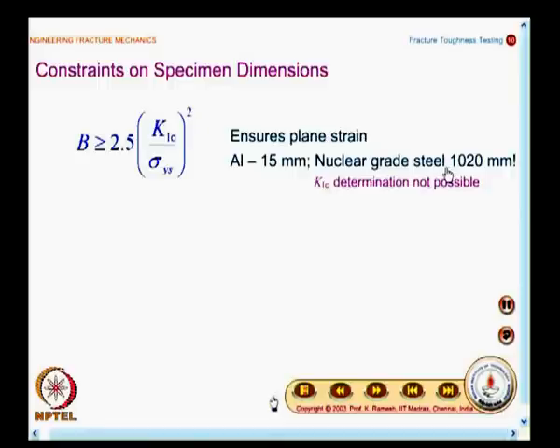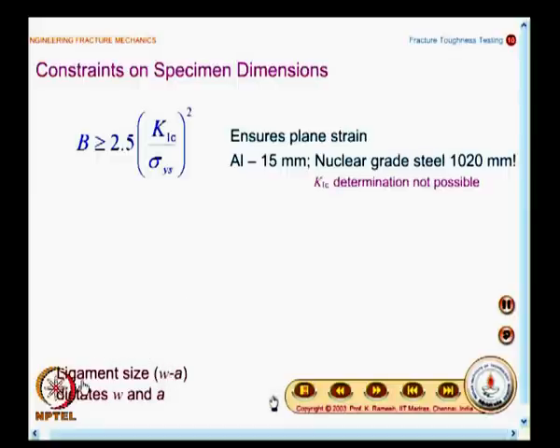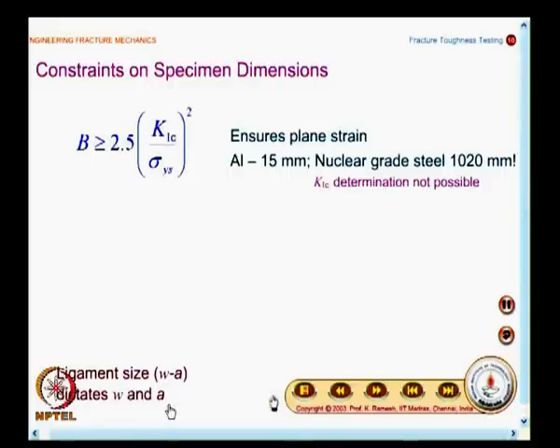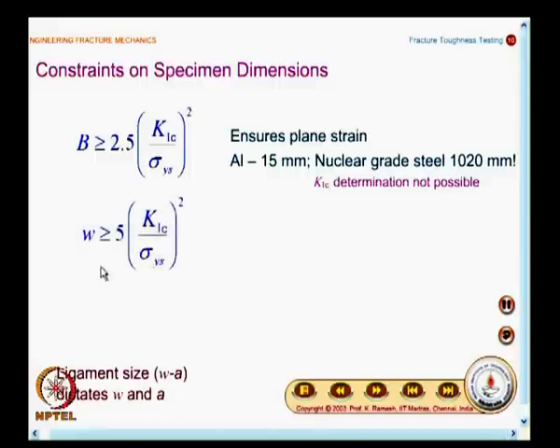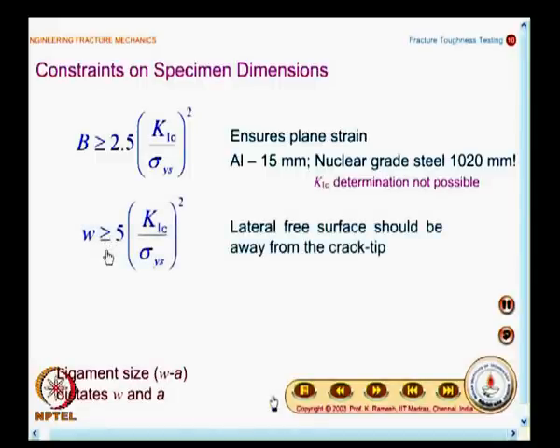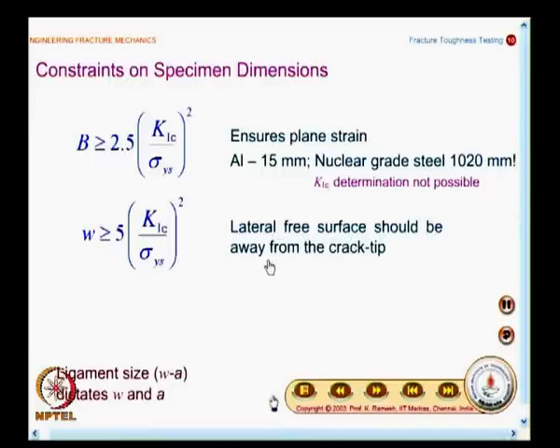That is the reason why people went for EPFM for nuclear grade steel. You have a plastic zone developed and you cannot have a 1020 mm specimen to break, so K1C determination is not possible. You also need to have considerations on what should be the size of the ligament, that is the length W minus a, which in turn dictates what W and a should be.